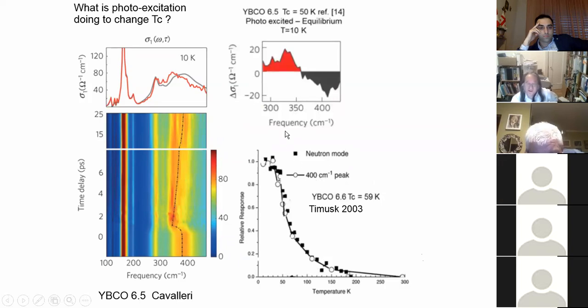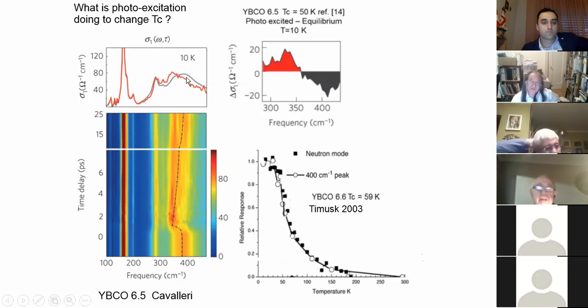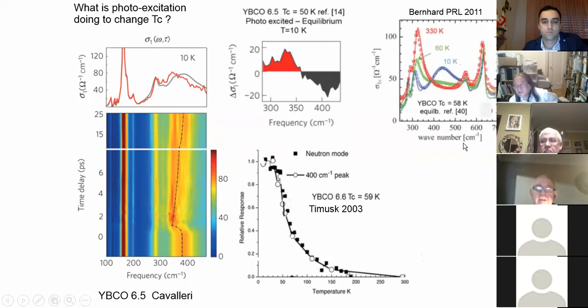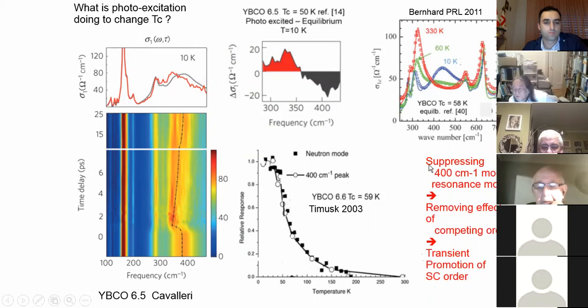And during the transient time scale, this original 400 Kayser mode was suppressed, and the intensity is changed to the lower energy region. And this is what the laser is doing. But without laser, the temperature can do the same thing. So at low temperature, you have this 400 Kayser mode. But at high temperature, that 400 Kayser mode disappears and gets to the lower energy. So this can be thought of as the 400 Kayser mode and the resonance mode coming from the same thing.